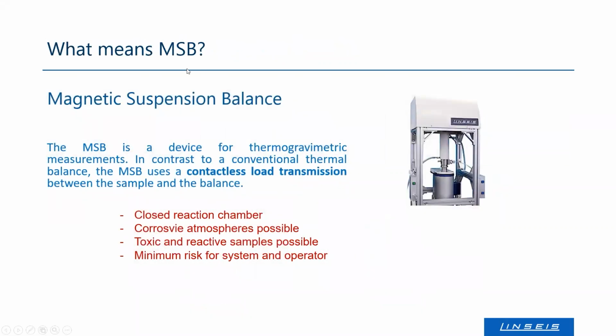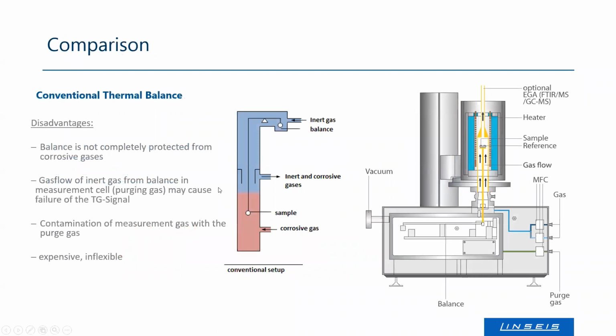So what does it mean? As I already said, MSB stands for magnetic suspension balance. So it's a classic device for thermogravimetric measurement, however, with a contactless load transmission between sample and balance. That means you have a closed reaction chamber. As said, you can measure corrosive atmospheres. You can measure even toxic and reactive samples, and there's a minimum risk for system and operator. In detail, I can show you a comparison, a schematic drawing of a classical conventional thermobalance you see on this slide. On the right side, this is the scheme of our STA PT1600 system.